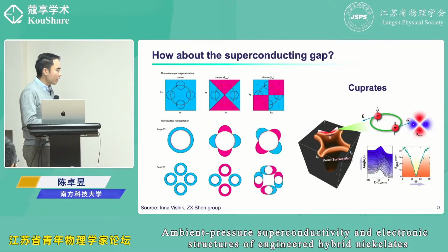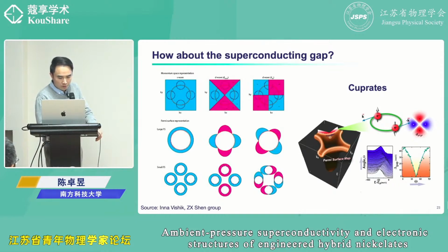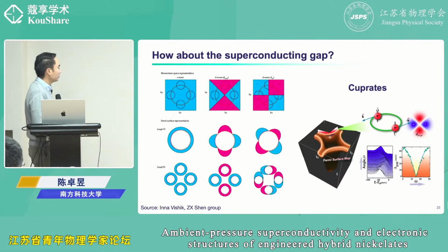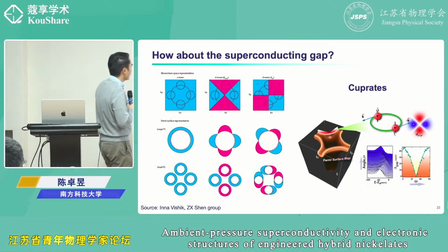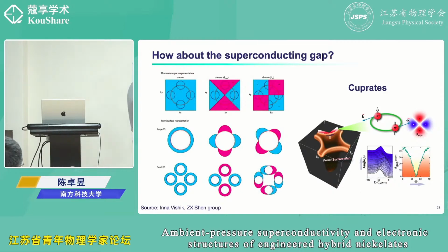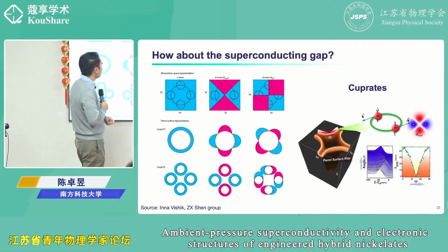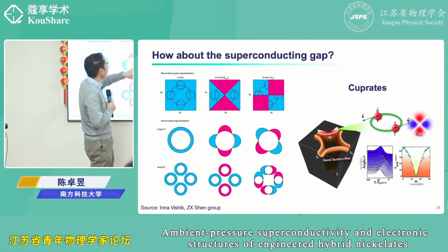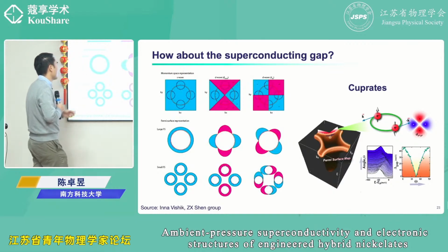Right. After getting the band structure, the next mission is to measure the superconducting gap. For nickelates, there are three possibilities: s-wave, d(x²−y²) wave, and d(xy) wave. These three possibilities will give you different measurement results from ARPES. For s-wave, you get a finite gap along all of the Fermi surface, and for d(x²−y²), because you have a sign change across this 45-degree diagonal direction, you will have a node at this point. The d(xy) is basically a rotation of 45 degrees compared to d(x²−y²).